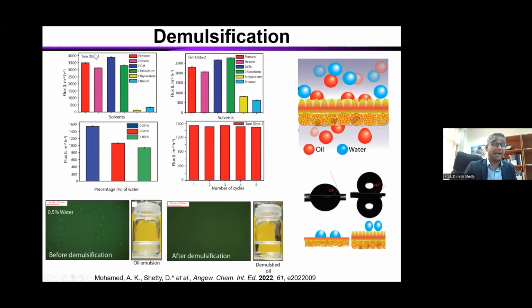As you can see, in case of hydrophobic system, you end up getting a good flux, because that is a very important criterion if you talk about separation. Very good flux for non-polar solvent. On the other hand, very poor flux for polar solvents like ethyl acetate and ethanol, understandable. In case of the less defect system, again you have a decent flux, but definitely this flux is less than the flux we are talking about for the other hydrophobic system. But on the other hand, it also has a decent flux for the polar solvent as well, which means this is not a great candidate. That's why we pursued with this hydrophobic membrane.